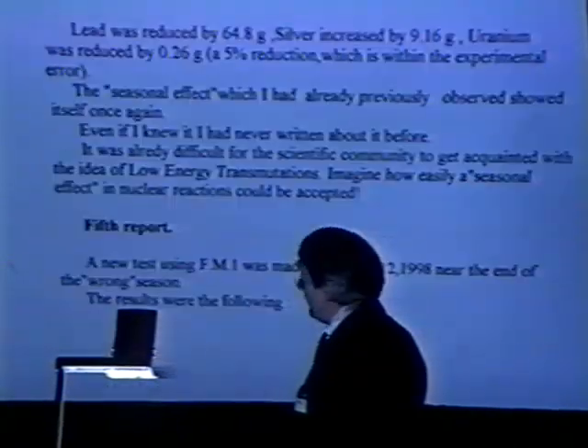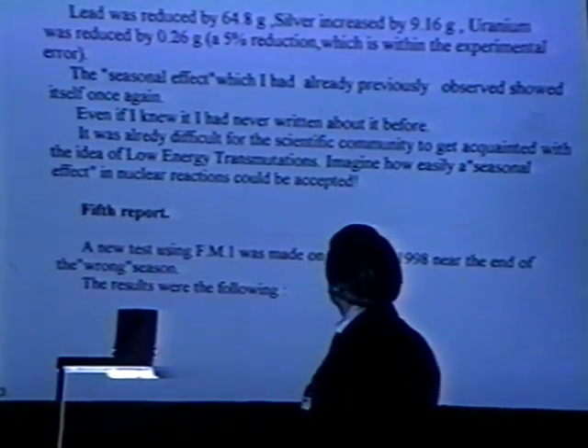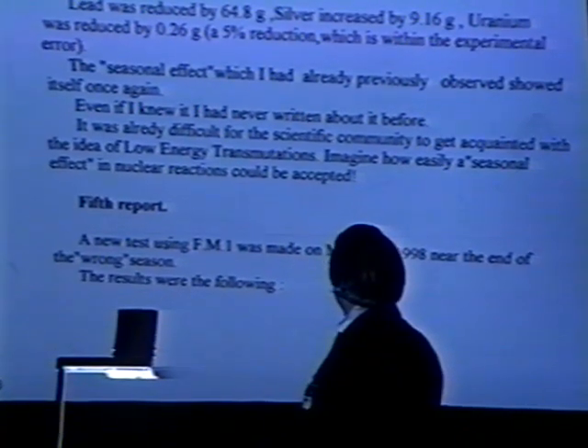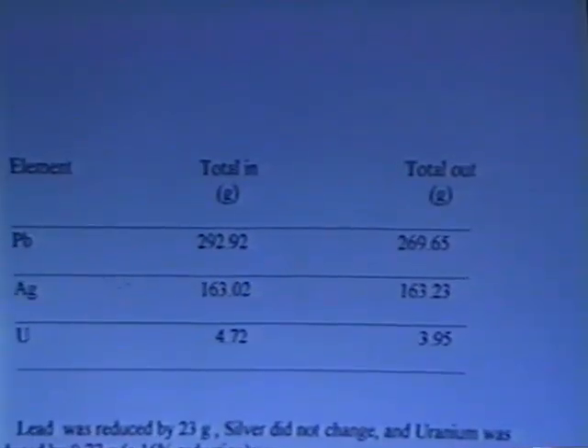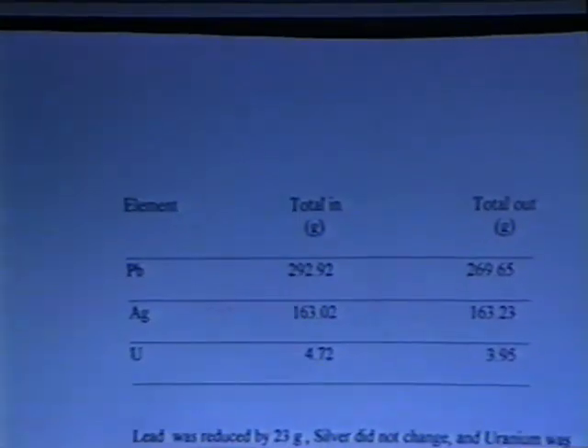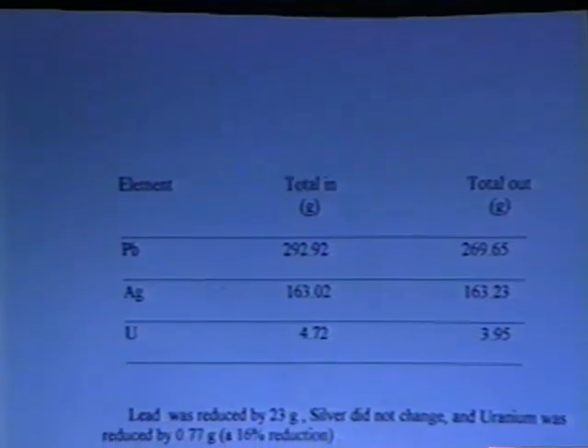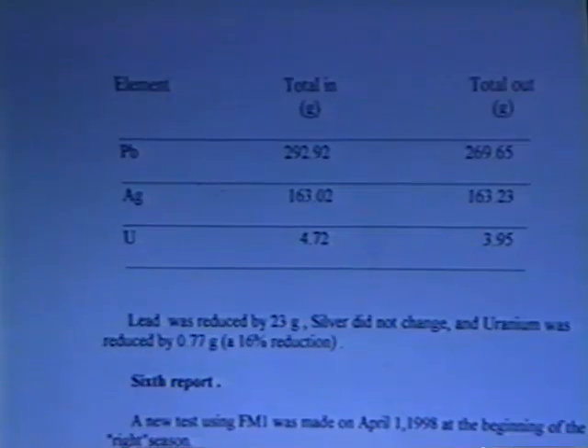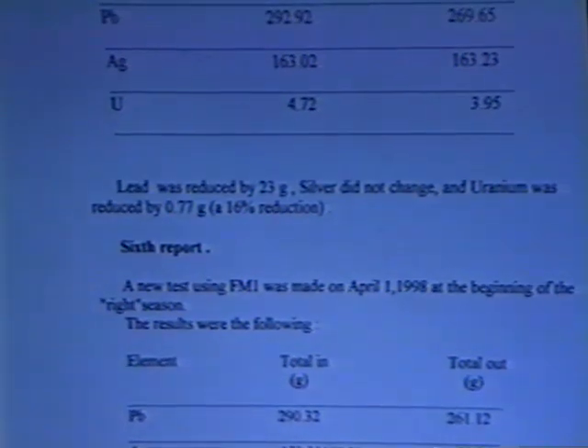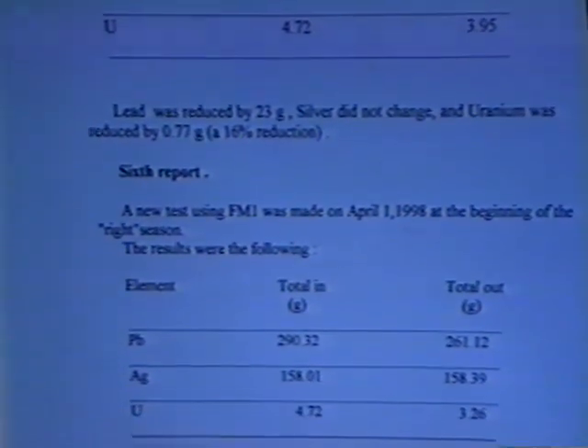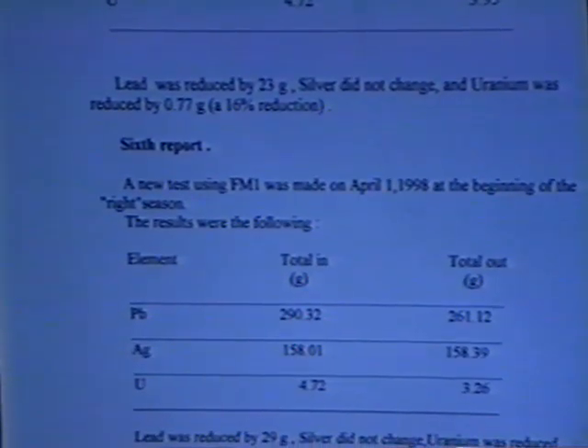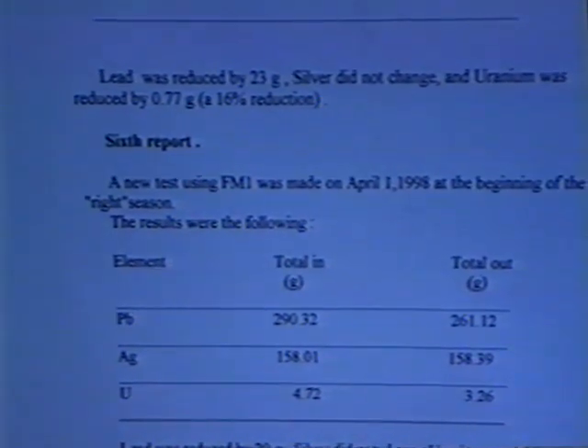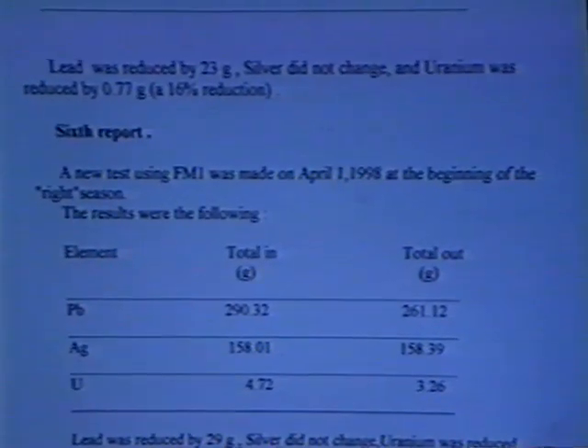After that, I made a further test on March 12, which is near the end of the wrong season. And the result was the following. Lead was reduced by 23 grams, silver did not change. Uranium was reduced by 0.77, a 16% reduction. Then on the 1st of April, I made a quick test just to present the results here. Lead was reduced by 29 grams, silver still did not change. Uranium was reduced by 1.46 grams, a 30% reduction.